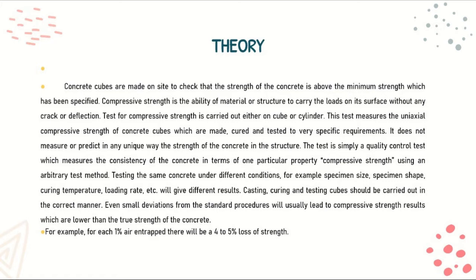Testing the same concrete under different conditions, for example, specimen size, specimen shape, curing temperature, loading rate, and others, will give different results. Casting, curing, and testing cubes should be carried out in the correct manner. Even small deviations from the standard procedure will usually lead to compressive strength results which are lower than the true strength of the concrete. For example, for each 1% air entrapped, there will be a 4 to 5% loss of strength.